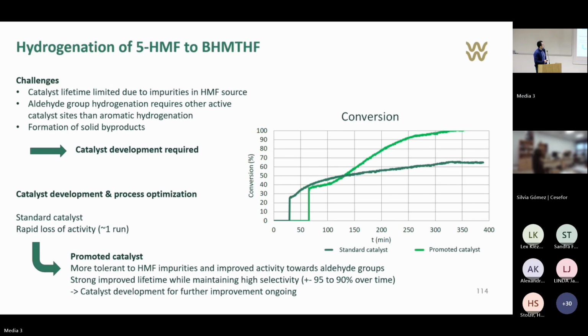And to hydrogenate an aldehyde group, we typically need other active catalyst sites than you would need for an aromatic ring hydrogenation. So in a sense, there is some catalyst development required. We could not use the same catalyst that we have for methyl THF.